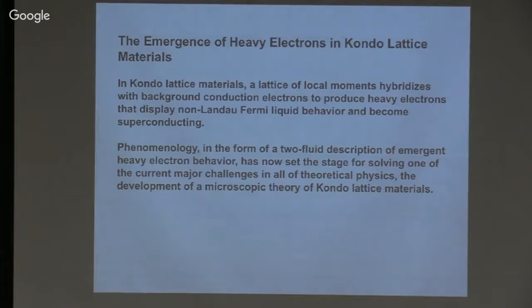So my final topic for you is to tell you about Kondo lattice materials. For those of you who are not condensed matter physicists, what's fascinating about these materials is that you start off with a lattice of local moments, usually f electrons, but can be d electrons. They are coupled to background conduction electrons. What you expect naively is, okay, this is going to be the single-ion Kondo effect writ large, in which the magnetic field of the local moment gets screened out by the conduction electron. This isn't what happens at all.